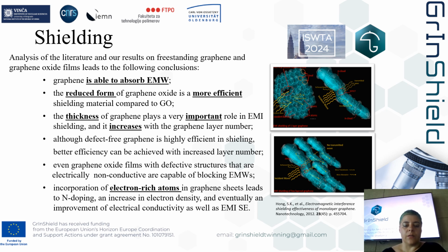number. And also the defect-free graphene, which is highly conductive, is very efficient in shielding, but better efficiency can be also achieved by increasing layer number. And here in the picture on the right, you can see one of the results from 2012, which shows the mechanisms of interference shielding for monolayer and multi-layer graphene. And also incorporation of electron-rich atoms in graphene sheets, or doping, can also eventually add improvements in the electrical conductivity as well as electromagnetic shielding of graphene-based materials.